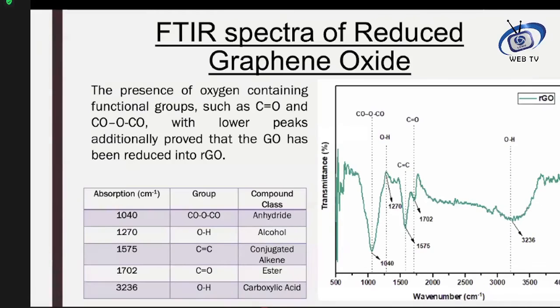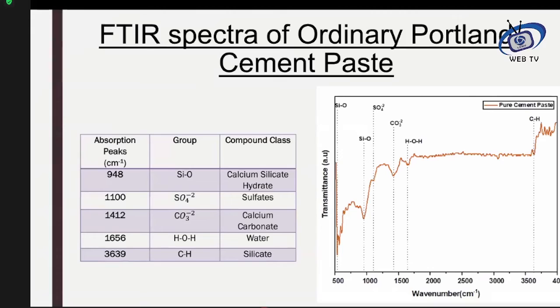The reduced graphene oxide was also tested with FTIR and shows that all of these peaks which are present in GO are reduced in their strength. And that is the FTIR spectra of the ordinary Portland cement used for this purpose, representing all the silicates, sulfates, and some water peaks. That was the characteristic spectra of the ordinary Portland cement.